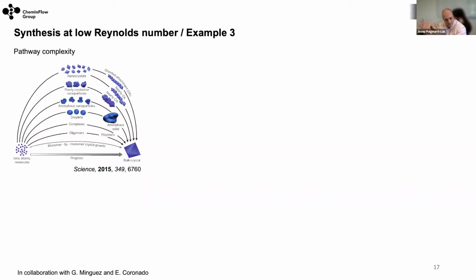And this is something that I've been working on lately. There are two communities that believe that crystallization processes can go different ways. There is the classical nucleation theory, where your ions or molecules assemble monomer by monomer to achieve the thermodynamic product. But then there are other researchers, for instance, one of the professors very active in this field is Professor Helmut Cölfen at the University of Konstanz, and they believe in mesoscale assembly. What they say is that it's not always that you go through a monomer by monomer assembly, but it can happen that you generate other structures that then organize and generate the final crystal structure.